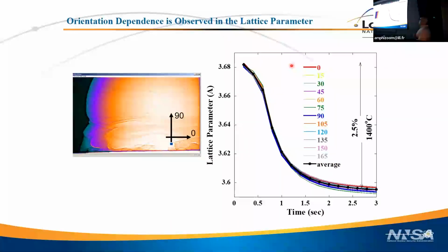Here's where we pull out the temperature. So this is showing the lattice parameter as you go around the ring of the Debye-Scherrer cone. So that's what 0 and 90 are referring to here. These are the lattice parameter along the different directions. 0 is parallel to the substrate, 90 is transverse to it. You'll see it comes down and you see a significant separation down here. So this is temperature. Going from here to here is the effective temperature. That's 1400 C is about what you go to from molten steel to room temperature. This little spread right here, that's stress.